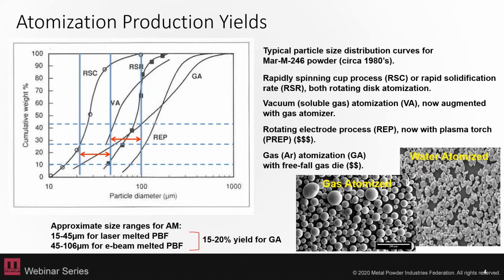And then again, looking at your atomization for your AM process feedstocks, those ranges are highlighted there: 15 to 45 microns for laser melted powder bed fusion, and generally the 45 to 106 micron size range for electron beam melted powder bed fusion. And if you're just looking at the gas atomization process, that's only about a 15 to 20% yield. So that moves into your cost range too, providing a higher cost because you're only able to use about 20% for your specific process, and then the rest of that has to be stored as inventory. So all of these factors need to be taken into account in terms of both safety and quality, because your production method is going to affect all of those pieces, and in the end, your cost point as well.